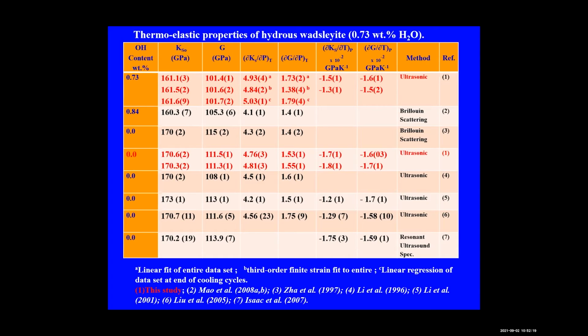Lastly, we can see that the reduction in the bulk and the shear moduli due to hydrogenation of the Wadsleyite from this study is compatible with the Brillouin scattering study shown here for Wadsleyite containing 0.84 weight% water.